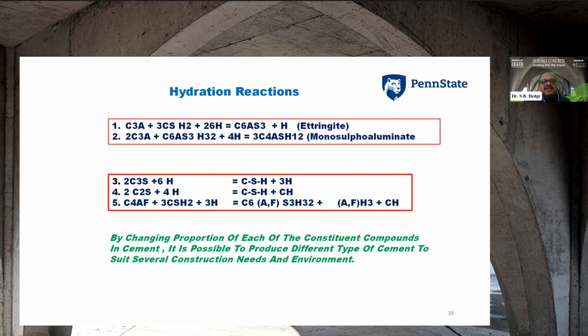These are the hydration reactions which I have shown: C3A reacts with water and gives ettringite, and C3A once again reacts with the leftover ettringite and forms monosulfoaluminate, and C3S and C2S give CSH gel, which is responsible for strength formation and strength generation. This is the reaction of the hydration.